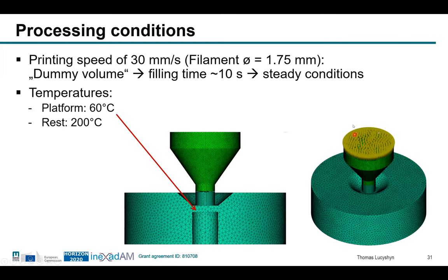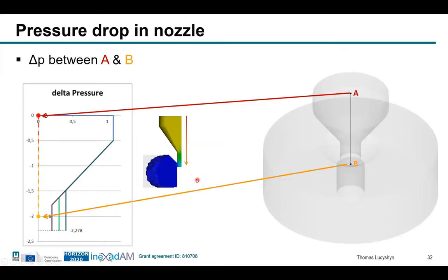So here is the injection location. The melt comes along here, this cross section, and then it goes into this smaller nozzle. One thing we had a look at is also the pressure drop between the entrance and the die gap, to see if we can simulate this, to know how much pressure is needed to squeeze the material through the nozzle. And as you can see here, most of the pressure drop happens in this nozzle. There is hardly any pressure difference in here. It's all the same pressure. It's basically ambient pressure, and then the pressure develops to this level.